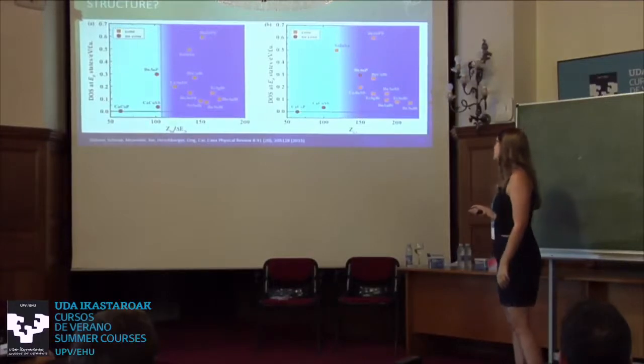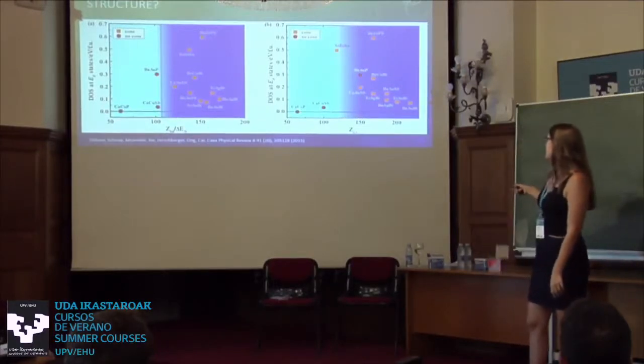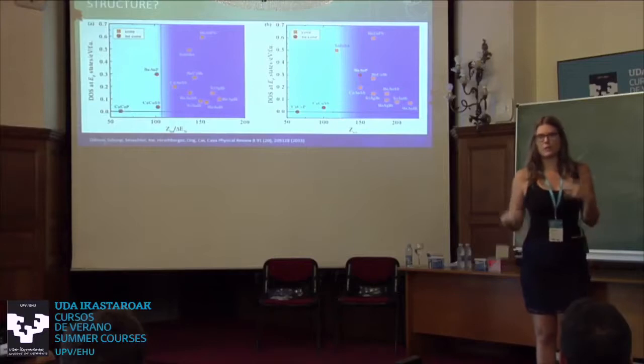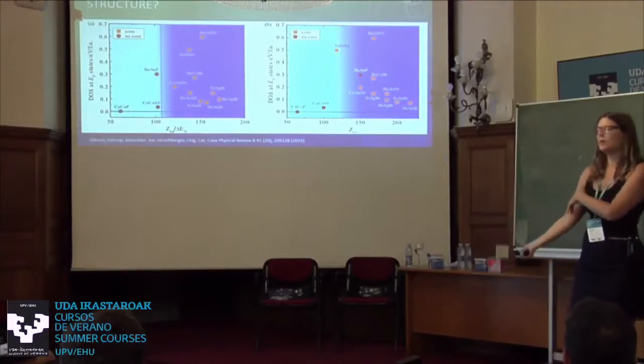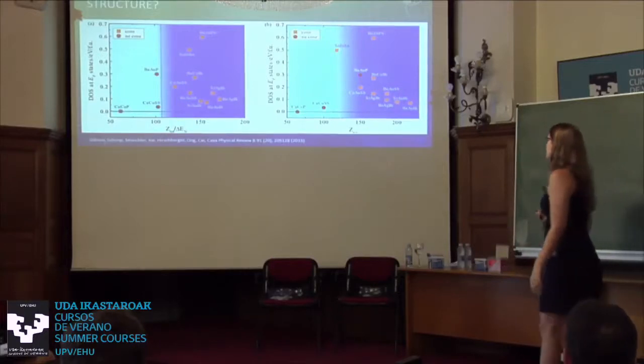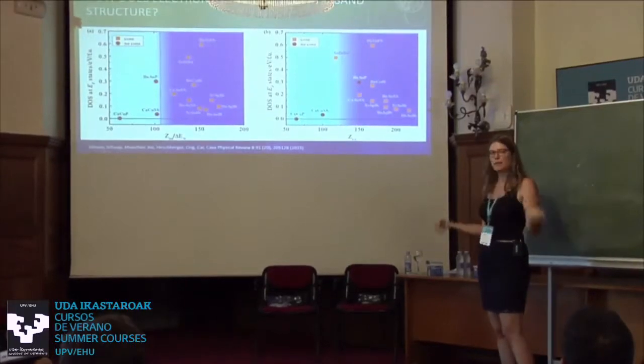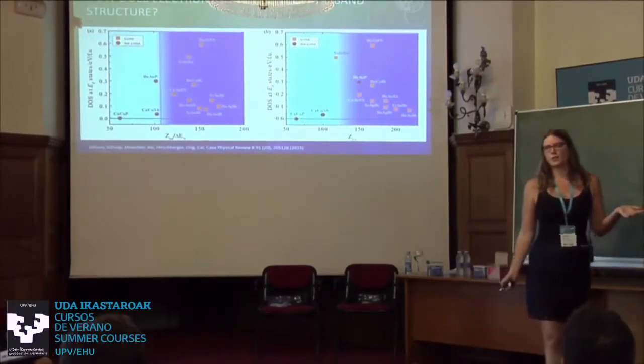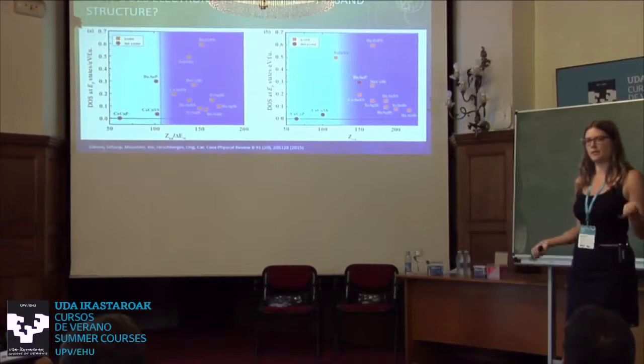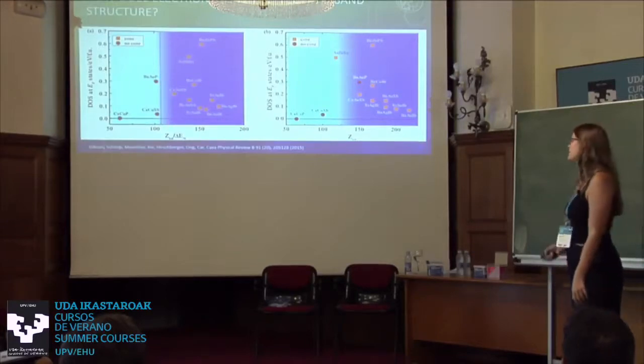However, we have a clearer trend if you just look at the nuclear charge on when there is a lower density of states at the Fermi level. So this means that the spin-orbit coupling, or the heaviness of a material, is important to reduce the number of states that are interfering with it. So we can find some trends here.